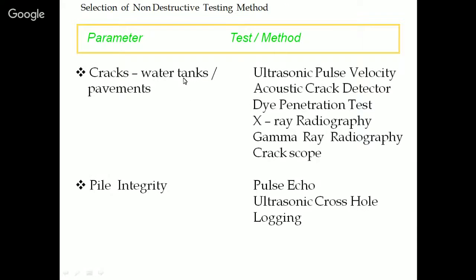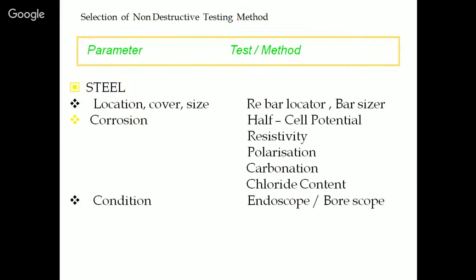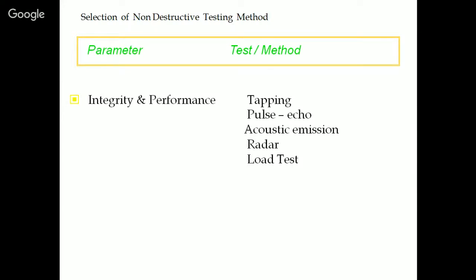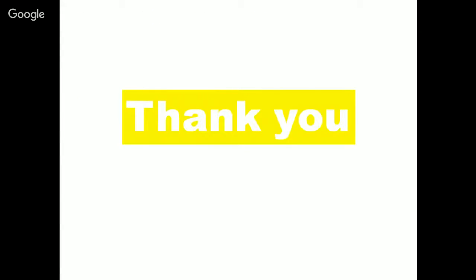Again, cracks and other things in water tanks, etc. We are using ultrasonic pulse velocity, acoustic emission, etc. Pile integrity test is again based on the propagation of velocity waves into your structure. In case of steel also we have tests like corrosion, where we are using the half-cell potentiometer, resistivity method, carbonation, chloride. For condition assessment, you can put a camera inside, generally the test called the endoscope and borescope. For integrity and performance, again acoustic emission, radar test, etc. can be used by using these methods.